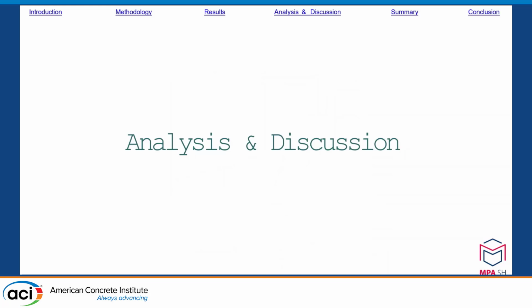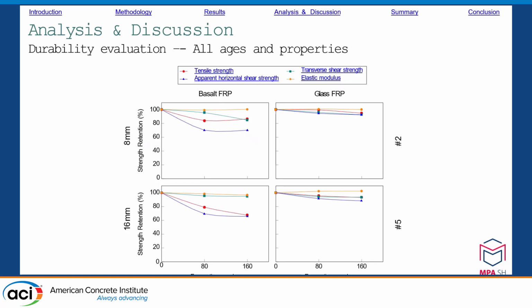Now I will come to my analysis and the discussion. The following graph summarizes all the results of the 3 tests just presented, as well as the modulus of elasticity. The results were converted in such a way that the retention capacity of the tensile and shear stress of the FRP bars can be recognized. The orange line shows the summarized results of the modulus of elasticity measurement. Overall, the modulus of elasticity of all test samples did not change significantly.